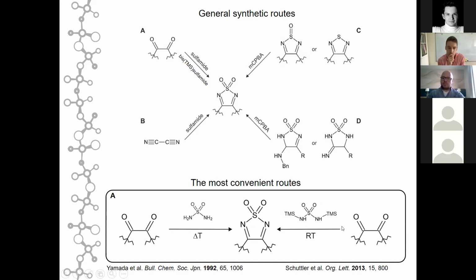This actually is more preferential, though it requires stricter synthetic conditions, because you have to exclude moisture from the synthesis, but the synthesis occurs at a low temperature. And this TMS sulfamide is more reactive and leads to dioxothiadiazoles that are not accessible via the sulfamide reaction.